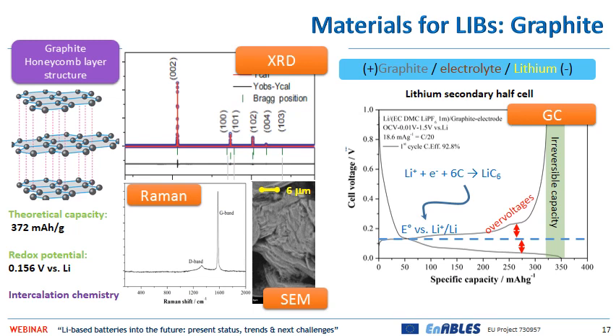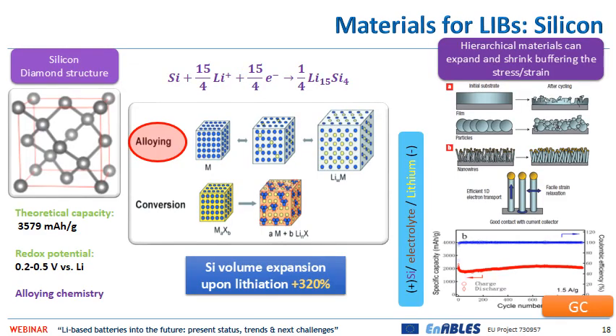The good news is that this degradation leads to the formation of the so-called solid electrolyte interface, SEI layer. That is a passivation layer that prevents further degradation in the second and in the following cycles. This means that graphite is able to operate as a reversible electrode when the SEI layer is stabilized. Obviously, the goal of a really good material is to minimize this irreversible capacity and to maximize the stability of the SEI layer.